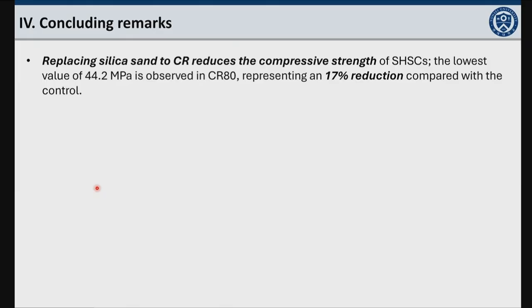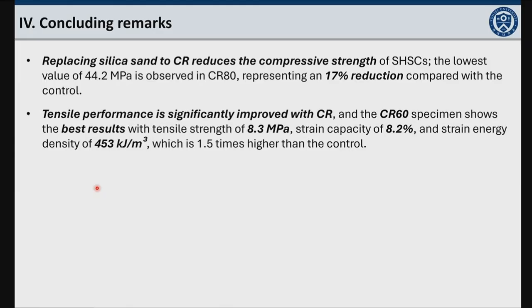The tensile performance is significantly improved with the crumb rubber, and the CR60 specimen shows the best result with a tensile strength of 8.3 megapascals, a strain capacity of 8.2%, and a strain energy density of 453 kilojoules per cubic meter, which is 1.5 times greater than the control sample.